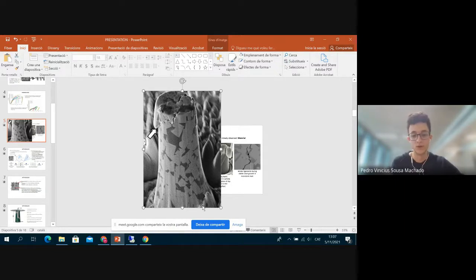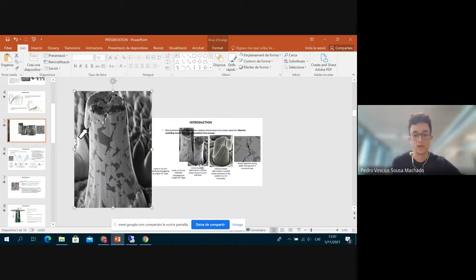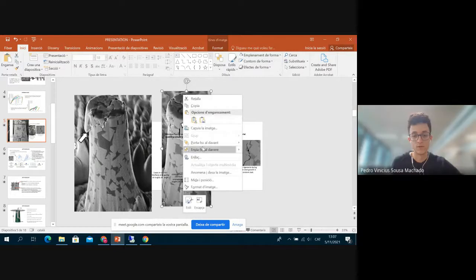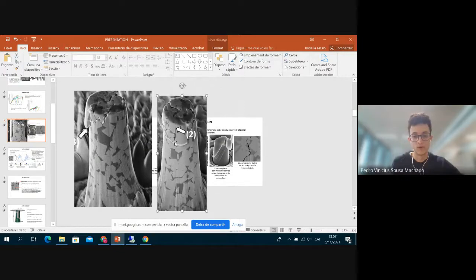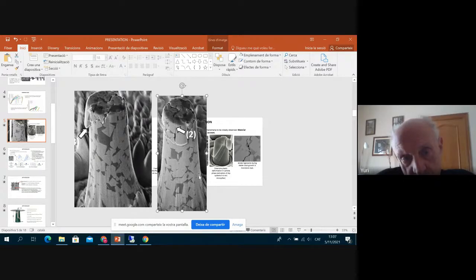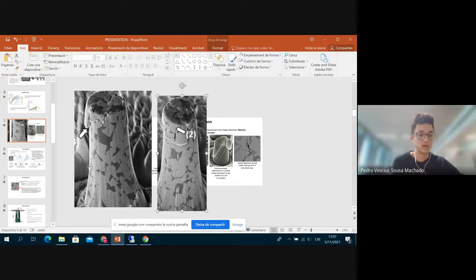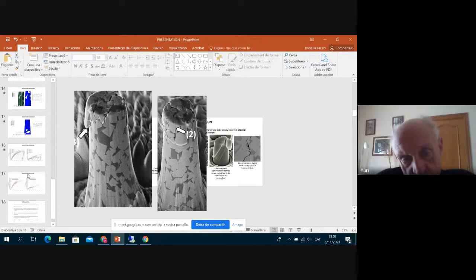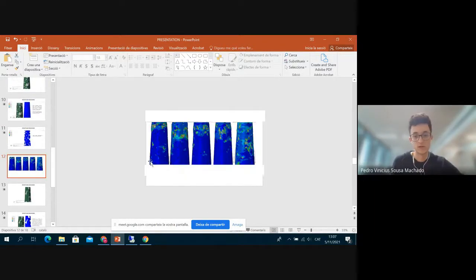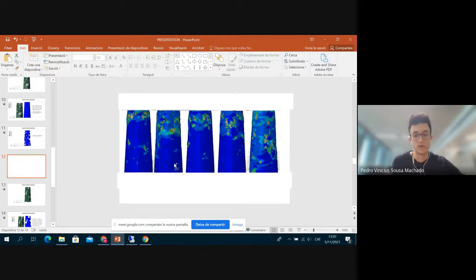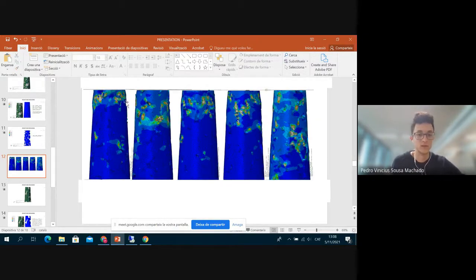It's not due to the deformation. These are not cracks. Then all the deformation, failure and cracks appeared on the top in this case, and it's more or less the same here, right? We also see this on the top. This is basically due to the taper angle, and in the simulations I matched the taper angle of the experiments so that the final result would be more similar to the experiments, and then we see more deformation on the top.